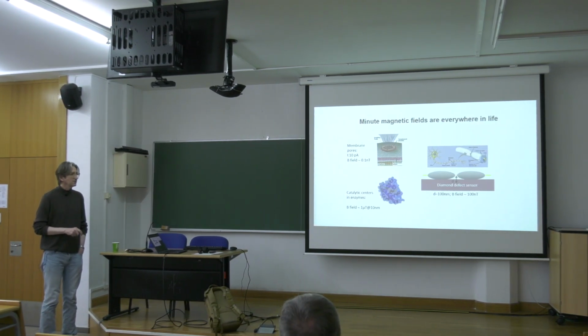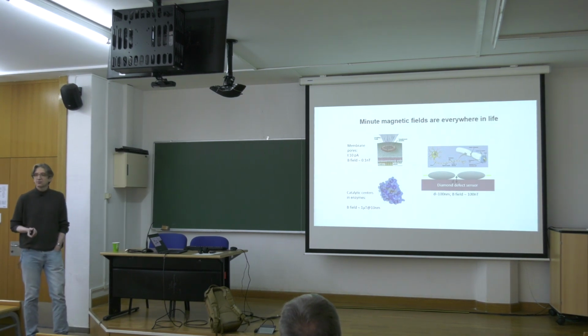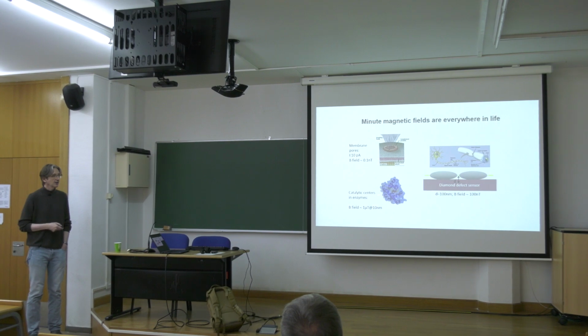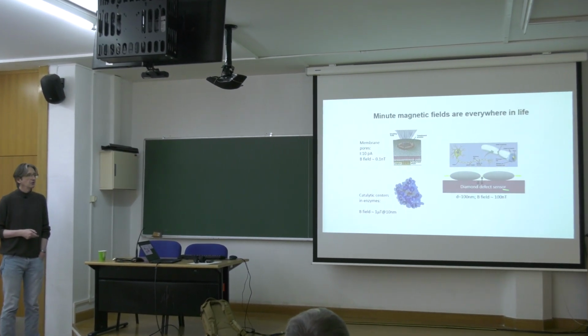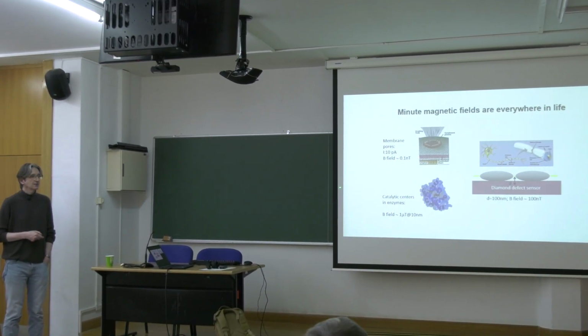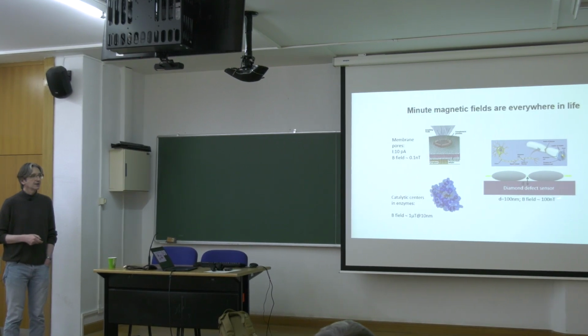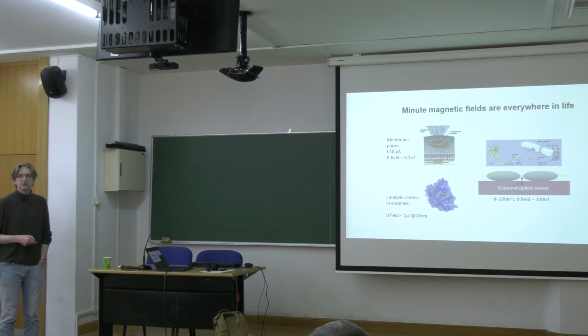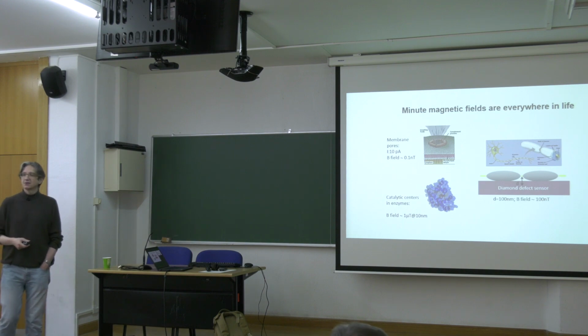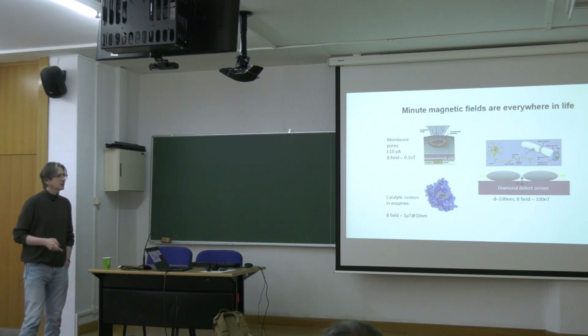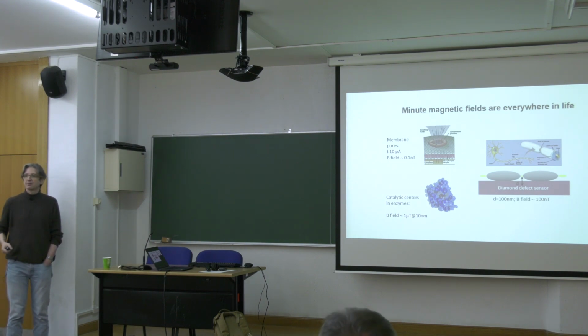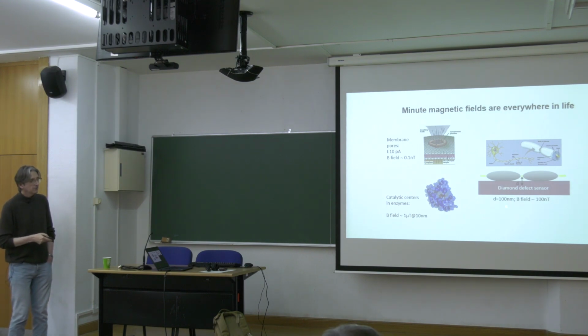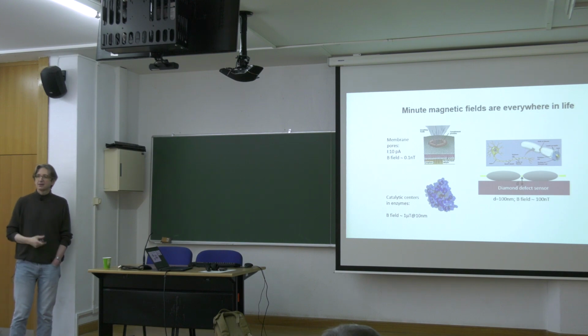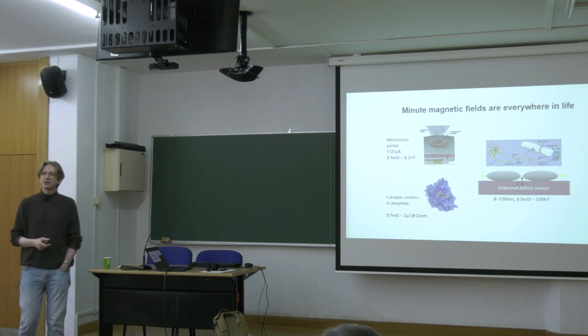Catalytic centers in enzymes make even larger fields coming from the electron spins inside of catalytic groups, which are on a microtesla scale if you are very close. Or neurons: when firing a signal, there is a current going through, and if you get very close to the neuron membrane, the field estimate can be on the order of nanotesla. If you are farther away, for example from the brain, the signals are very weak, on a femtotesla scale. But if you get very close to the membrane, it is expected that the magnetic field coming from the neuron signal is larger.